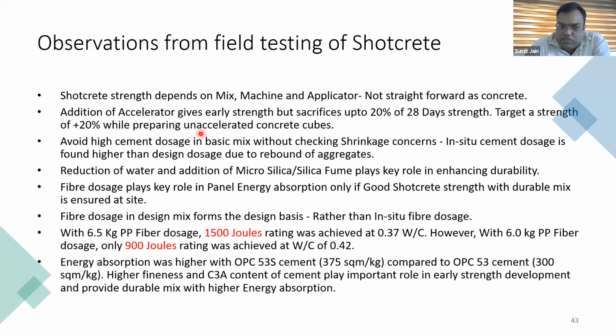Then the fiber dosage in the design mix forms the design basis rather than the in situ fiber dosage. Actually, this is the same as the aggregates getting rebounded; the fibers also get rebounded. So as per the European norms, when we want to check the fiber content, one should measure the fiber content right at the pouring point, not at the application point.